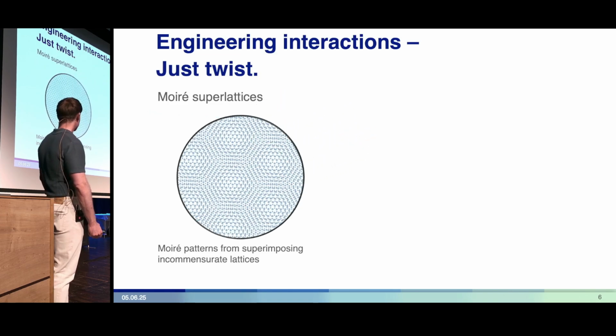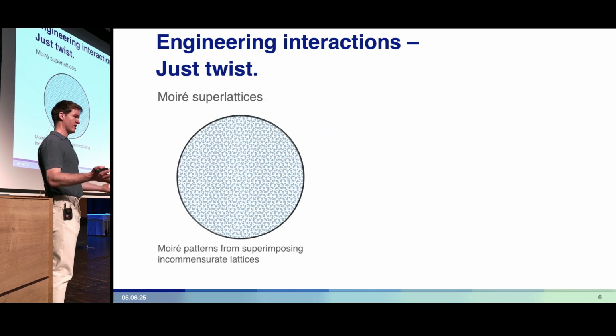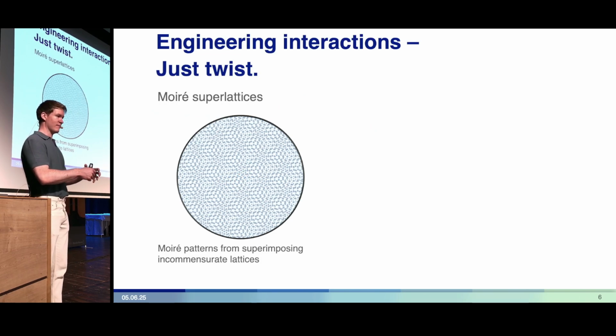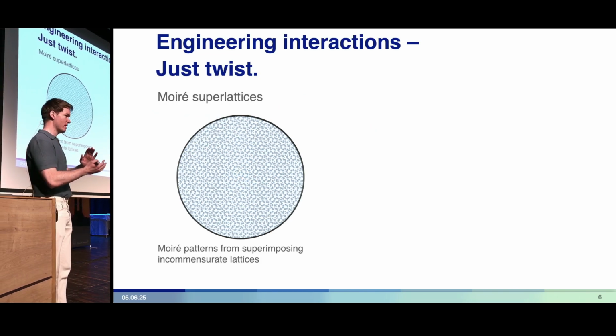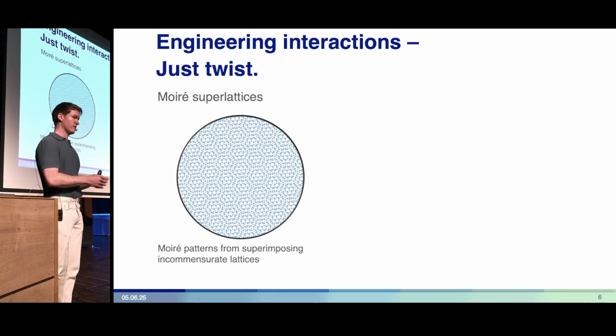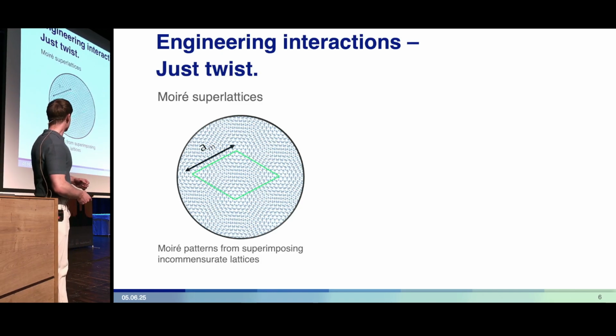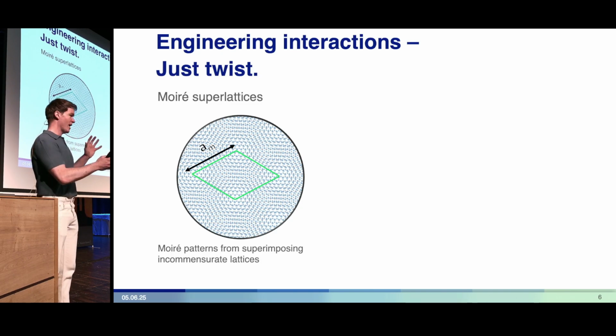So a Moiré superlattice happens when I take two layers of semiconductors and put them together, and they must be slightly incommensurate. Either there's a small twist angle between them or there's a small lattice mismatch. But you form this spatial beat pattern between the two crystal lattices, and you have a new, enlarged periodicity in the system, a Moiré pattern.